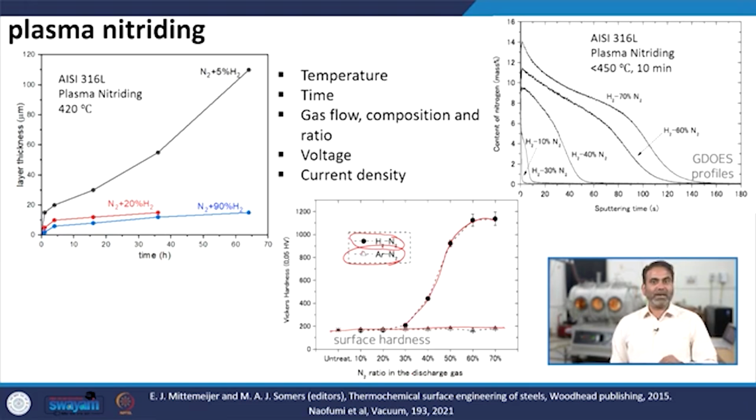In the absence of hydrogen, I think whatever nitrogen ions you create recombine and form N2 gas, rather than diffusing into the solid. That is the understanding we can have. That means hydrogen is needed in the nitrogen plasma nitriding, in addition to molecular N2 gas.